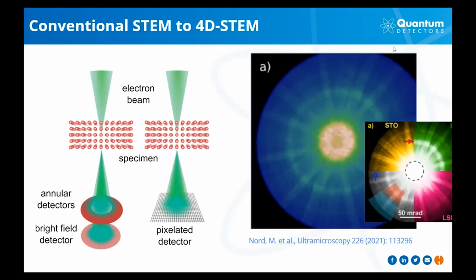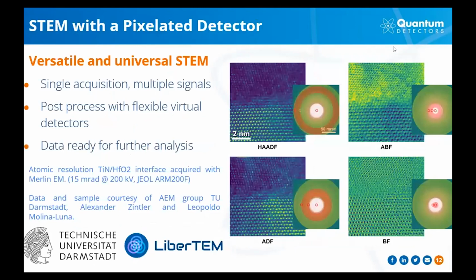And so when we collect data sets like this, we collect them for every point of a 2D scan. Hence, we create 4-dimensional data sets and the name 4D STEM technique. Just to mention, we can see phase contrast information in the center of the diffraction pattern. We have some higher order Laue zone rings across and Kikuchi bands through the image. All of this would be summed in the annular detector. Because we've collected this information about the STEM experiment, we can easily recreate this standard STEM data after, in post-processing.